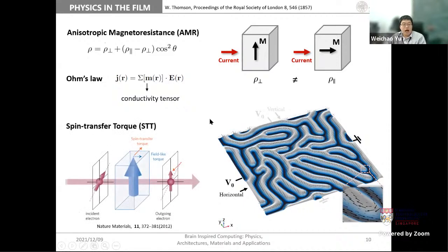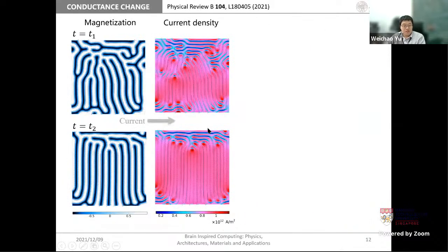Secondly, we have spin transfer torque, STT. When the current, the spin, the electrons flow through the magnet, the spin carried by the electrons will interact with the local magnetization, which can induce the so-called spin transfer torque, which means the magnetic textures can be driven by the electric current. So briefly speaking, when we apply electric current, it drives the texture, leading to the change of the conductance state. And let's see the simulation.